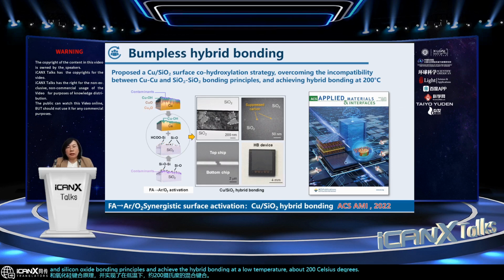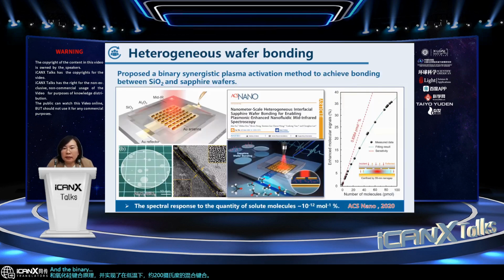And a binary synergistic plasma activation method is also proposed by our team to achieve bonding between silicon dioxide and sapphire wafers, enabling the fabrication of ultra-sensitive mid-infrared spectroscopic detection devices. So we achieve a very high resolution of the response of the spectrum to the number of solute molecules.